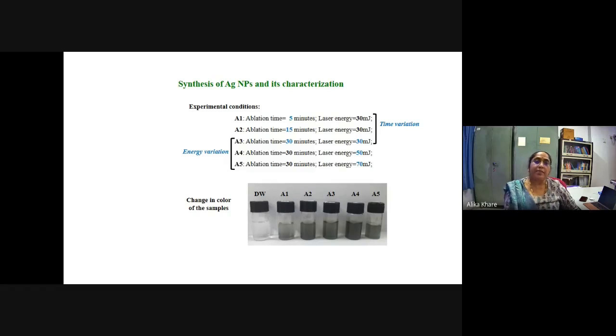Another example is the silver nanoparticle. Again we have changed the time and the laser energy. One can see the laser exposed to the liquid, and the color is not appearing properly in this photograph, but the color was changing since the particle size is changing, and of course the concentration was also changing a little. With the change in particle size, since the SPR is changing slightly, the color is changing.